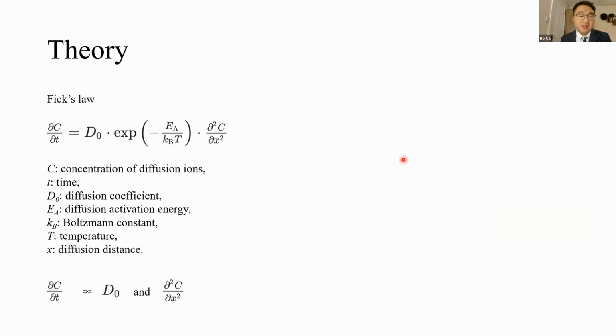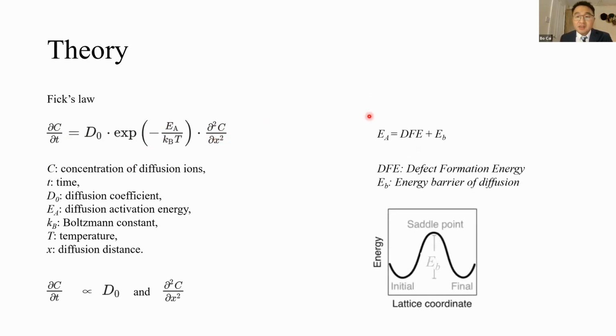A better understanding of this phenomenon would help us to solve the problem through a more reasonable method. First of all, the diffusion follows Fick's law. The left side of this equation is proportional to D0 and this term, where the activation energy EA can affect the left term by an exponential relationship. So I think EA is the most important in this equation. EA is equal to the defect formation energy plus the energy barrier EB.